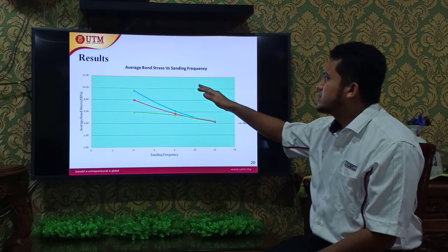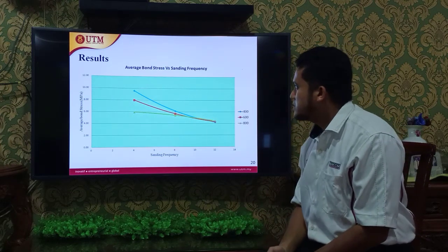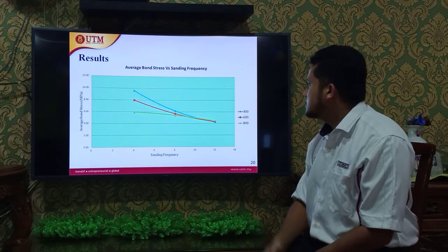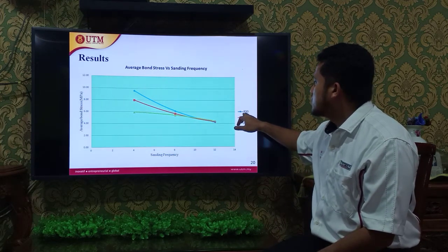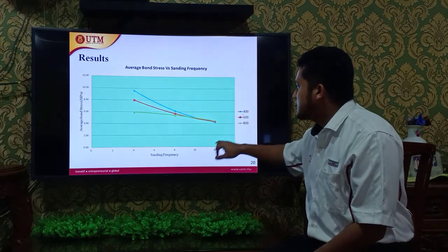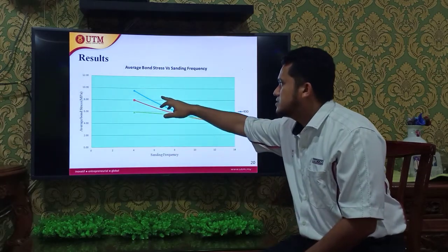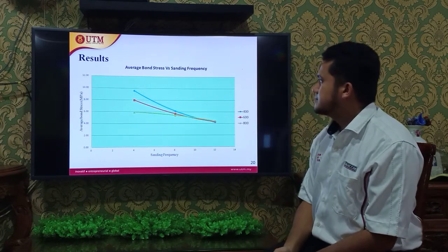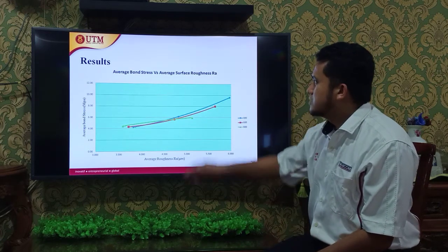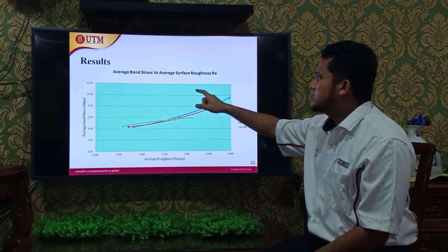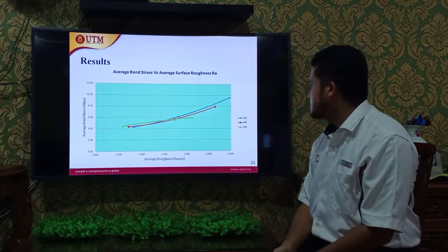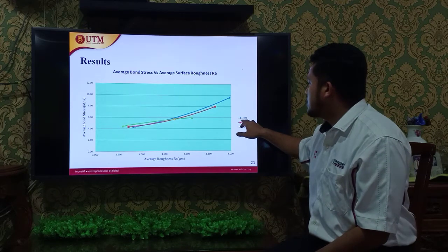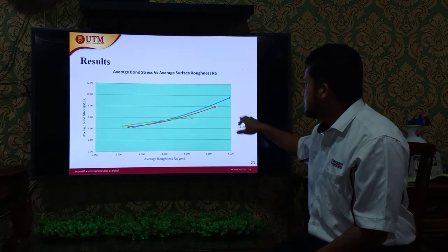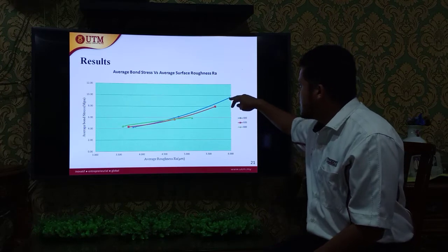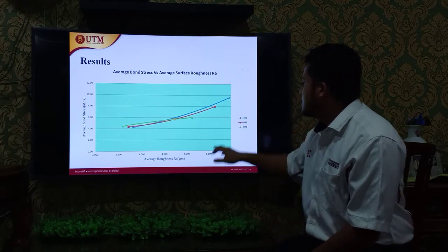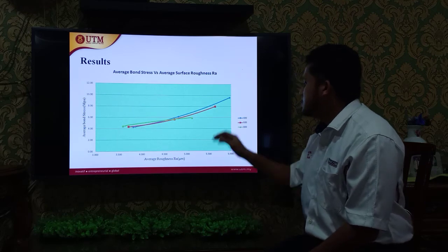Okay, this is the average. This is a graph of average bond stress versus sanding frequency. As we see, grit size 400 with a sanding frequency of 4 times is the highest for average bond stress. This graph is average bond stress versus average surface roughness. As for grit 400, it is the highest for average bond stress, and the surface roughness is highest.